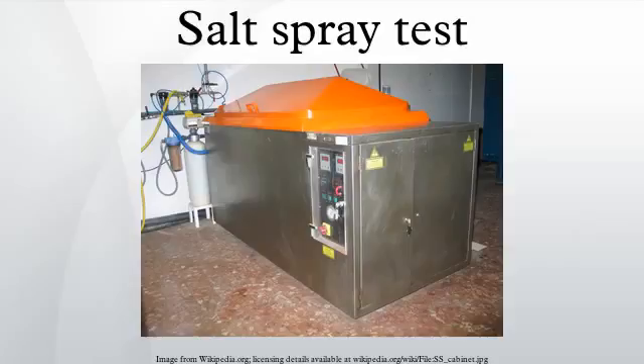Test specimens are placed in an enclosed chamber and exposed to a continuous indirect spray of salt water solution, prepared in accordance with the requirements of the test standard and acidified by the addition of acetic acid. This spray is set to fall out onto the specimens at a rate of 1.0 to 2.0 ml per 80 square centimetres per hour, in a chamber temperature of +35 Celsius. This climate is maintained under constant steady-state conditions. The test duration is variable.